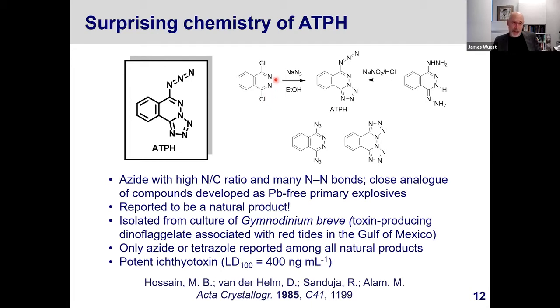You can make it just by taking dichlorophthalazine and doing substitution with azide. One of the substituted azides cyclizes in a characteristic azide-tetrazole isomerization. You can also make the compound by diazotization of the corresponding dihydrazinophthalazine. It's interesting that the preferred structure of ATPH is this azide-tetrazole and not the diazide or the bis-tetrazole. We've done computational work that suggests that you can explain this on the basis of the interaction of these two groups. What makes ATPH surprising is that it is also a purported natural product.